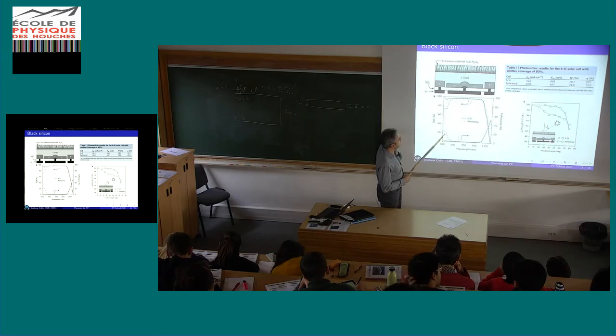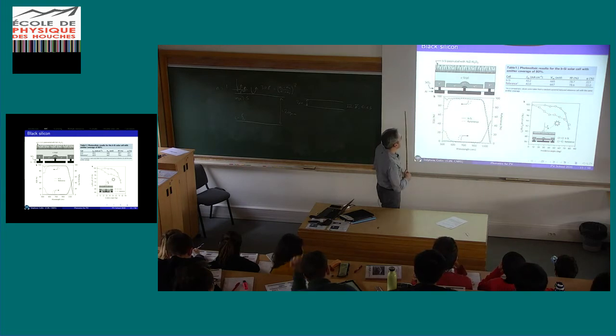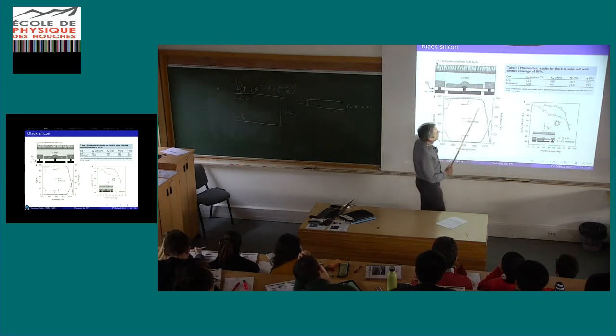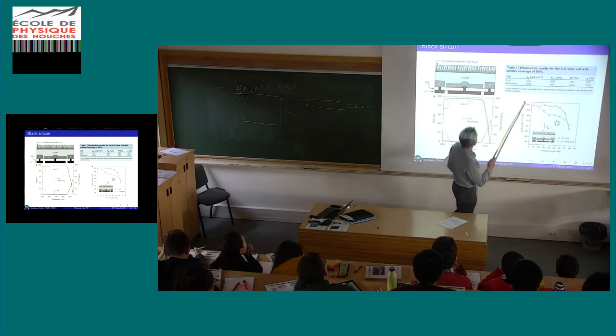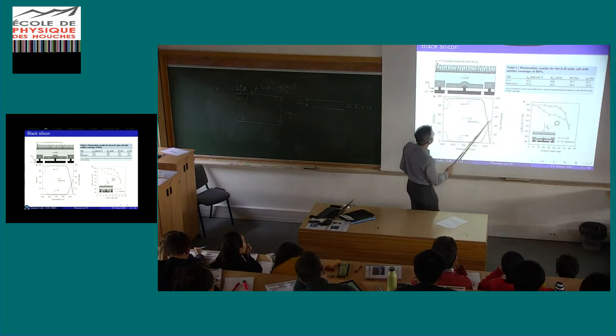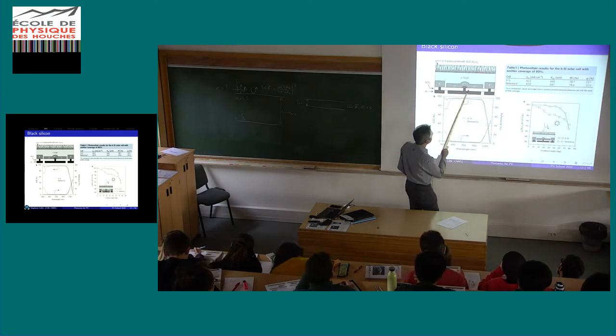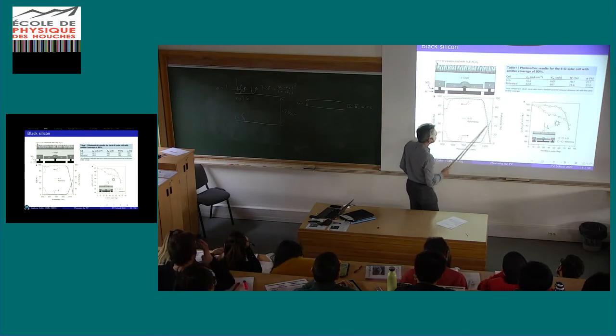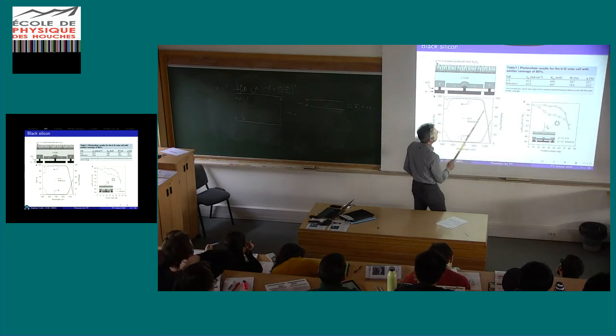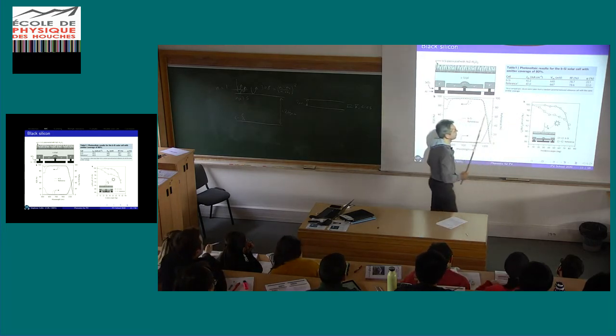Okay, here the results are pretty good. You increase the external quantum efficiency in this region, but finally, due to a decrease at larger wavelengths, probably mainly due to the fact that you etch the silicon, you lose silicon material as compared to the reference. You lose a bit here, and finally you have nearly the same short circuit current.